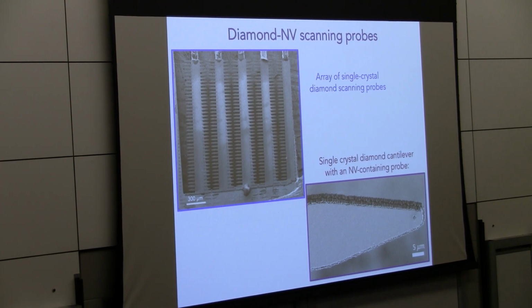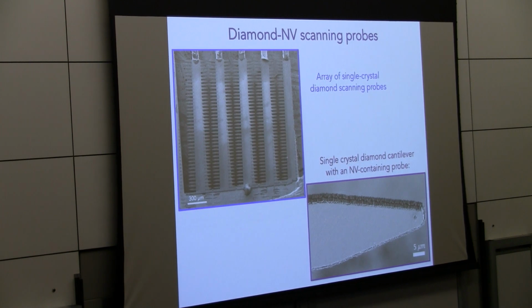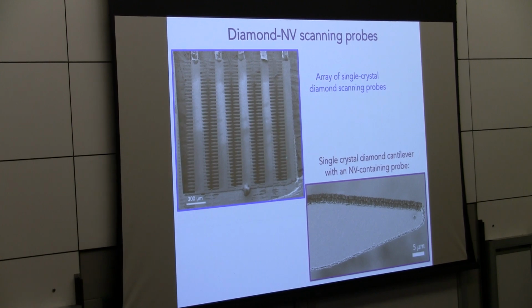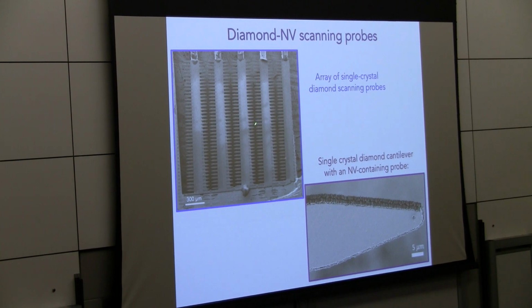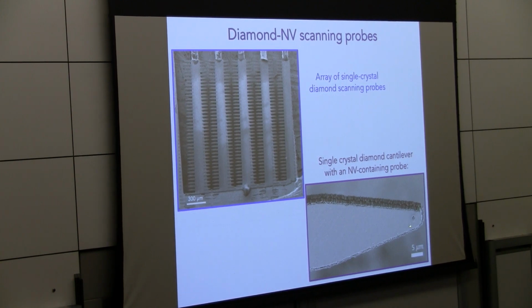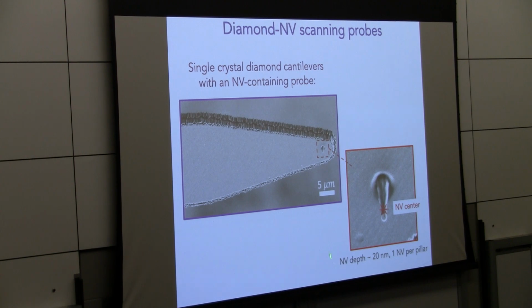First of all, we had to make these diamond probes. I'll spend 2 slides on this, a lot less than the actual students' time spent making these types of structures. So the short story is fabricating single crystal diamond is not straightforward. There's a reason why diamond is a very robust and good material. It's not easily etched by much. But what we do is we make an array of hundreds and hundreds of these diamond single crystal cantilevers. And at the end of the cantilever, we etch a little pillar, which is going to be our tip. That's a zoom in of this little pillar, and we engineer there to be a single NV center that resides within 5, 10, 20 nanometers of the surface.